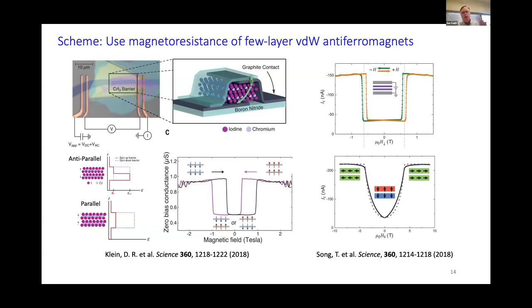So we wanted to take this work and see if we can look at the high frequency signals as well once we start exciting the magnetic dynamics. And this requires some changes from what's been done before, mostly in the way of microwave engineering. You want to reduce the impedance of the junctions so that they're not too far from 50 ohms, and you want to reduce some of the nonlinearities that are naturally there so you don't have large background signals. I won't go into too much detail about that, but those are some of the things we've had to worry about.